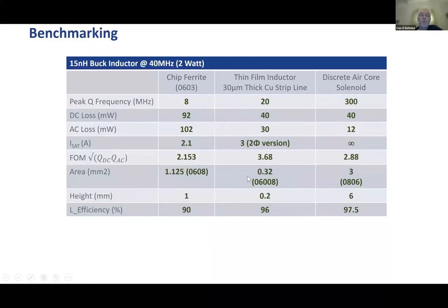And of course, the other thing that's important is we talked about energy saving, so the efficiency is really important here. You can see for ferrite, 90%, 96% for the thin film and 97.5% for the air core. And we have been able to demonstrate that 96% figure.